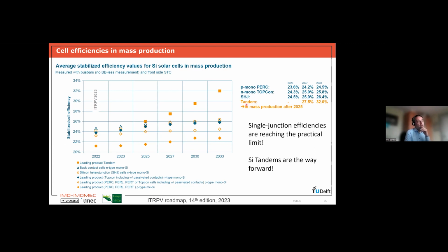And for the tandems, of course, which I will explain later, these are still being developed. They are not in mass production yet. But in the long run, the idea is that this will allow us to go even much higher in efficiency. So silicon tandems are really the way forward, also how the industry sees it. These single junction efficiencies for silicon, close to 26%, that's really more or less the practical limit of what we can achieve. And that's why we need these silicon tandems to go further than that.